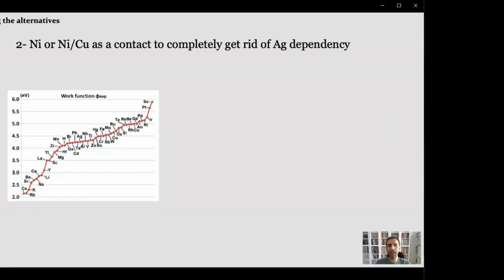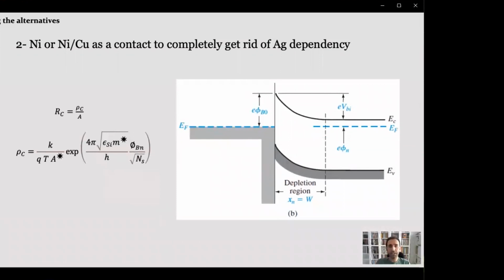This detrimental effect is caused by Fermi level pinning. Fermi level pinning arises from the surface states of the semiconductor and happens for most used semiconductors such as silicon. The contact resistance, or the measure of the Schottky barrier height, is governed by this equation. Here, rho C is the specific contact resistance that we can measure, and it depends on the doping concentration. That's where the selective emitter contacts come in. Increasing the doping concentration in this equation, we can decrease the specific contact resistivity and ultimately the contact resistance itself.